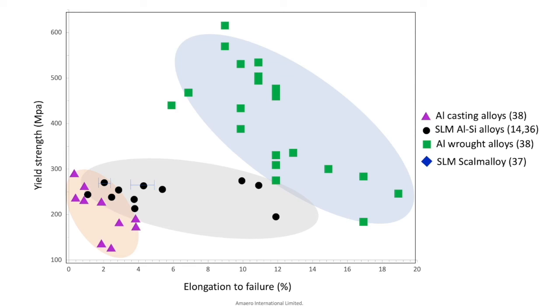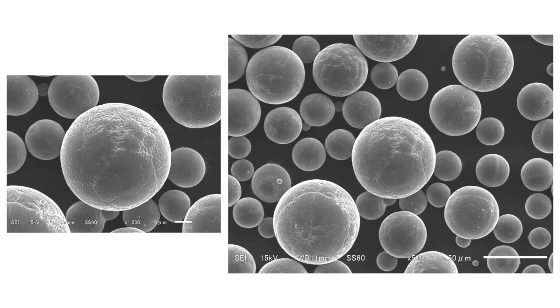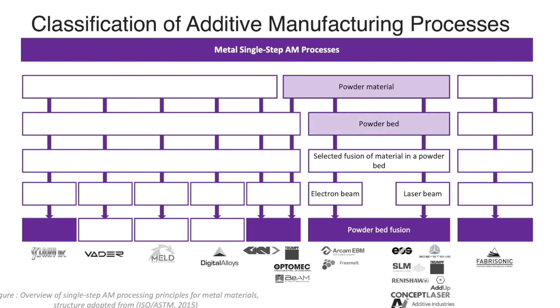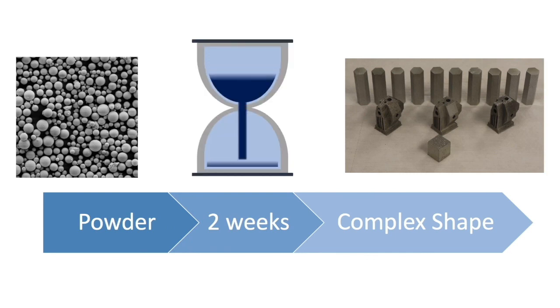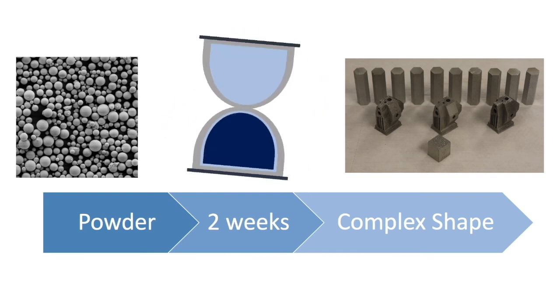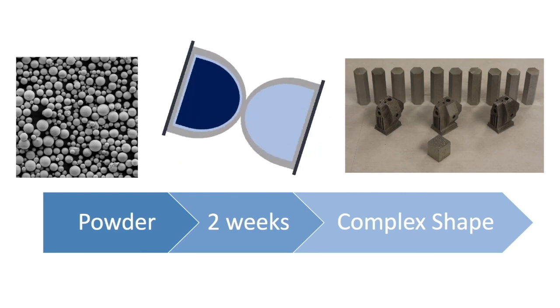Our group chose to investigate Scalmalloy as it is the most mature, high-strength aluminum alloy available that is not susceptible to cracks during manufacturing. The Toyal group supplied the sample of Scalmalloy, which were ultraspherical powders with low oxygen content that is beneficial for all metal additive manufacturing technologies. This material was a good option for our group to demonstrate process parameter optimization in laser powder bed fusion. Laser powder bed fusion provides unique design freedoms and opportunities for structural lightweighting. We set an ambitious goal of going from powder to maximum density parts with good surface quality in less than 2 weeks. This is an ambitious goal for laser powder bed fusion process parameter development, where the optimization cycle may take months.